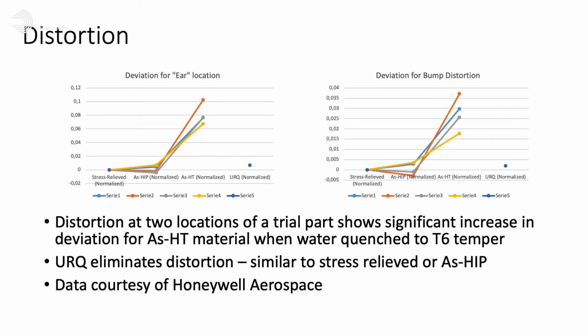The results from a dimensional study that our partners at Honeywell Aerospace conducted were also very positive. We did not notice any significant distortion from the quench after the HIP process in the URQ system. They ran a couple of trial parts and measured distortion values at some representative locations and found values that were more in line with stress relief only or HIP only processes, and much, much lower than what they were observing in water quench. Distortion is a measurement that has to be taken in the context of the customer's needs, and the feedback we received from Honeywell was that this would meet their needs. So that's really a win for them.